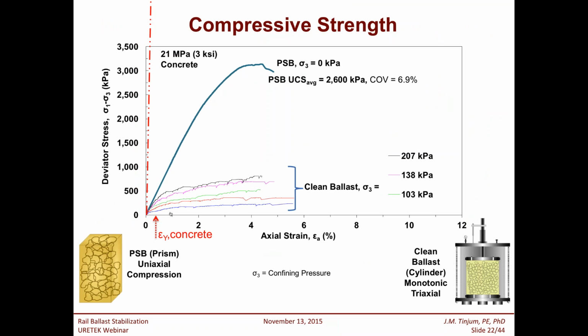In this first graph, you're going to see how it improves the compressive strength of the treated ballast section. What you're seeing in this graph is that clean ballast is going to have compressive strength on the order of 500 to no more than 1,000 kPa. And I apologize for the SI units for some of you that are still hoping everything was in PSF. We are a university, and most of our research is published in SI. But relative to that scale, you see that the polyurethane stabilized ballast is significantly stronger than clean ballast, but well less so than concrete.